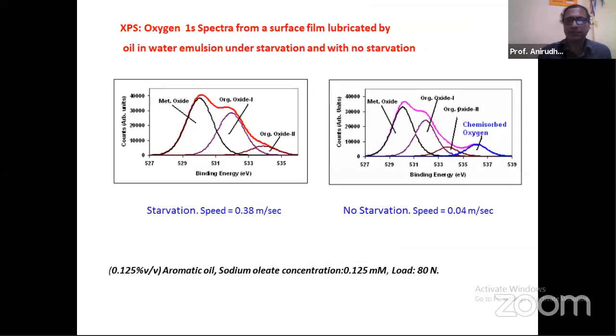And then this is the oxygen 1s part of that spectrum from those two films. Previously, we looked at the film for carbon information. Now we are looking at the oxygen information from those same films, under starvation and without starvation. Now, what is conspicuous here for the oxygen information is that when there is no starvation, or in other words, when it is more lubricious, exhibiting very low coefficient of friction, there is a presence of chemisorbed oxygen which gets formed under no starvation, which means it is at very low sliding speeds.